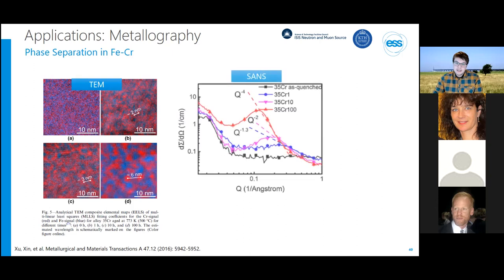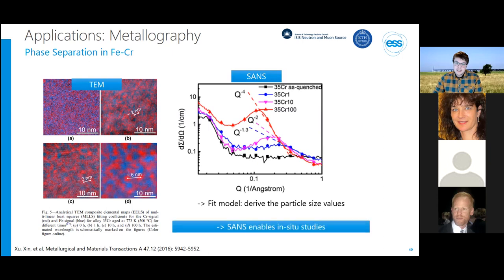And small angle neutron scattering, on the other hand, can provide representative sampling volumes, so much bigger samples. And when fitting the data, one obtains the average size distribution in there. And what is moreover really an intrinsic advantage of using neutrons is the fact that this can be performed in situ and in operando. Especially if you've ever prepared samples for a TEM, you know how cumbersome that can be.